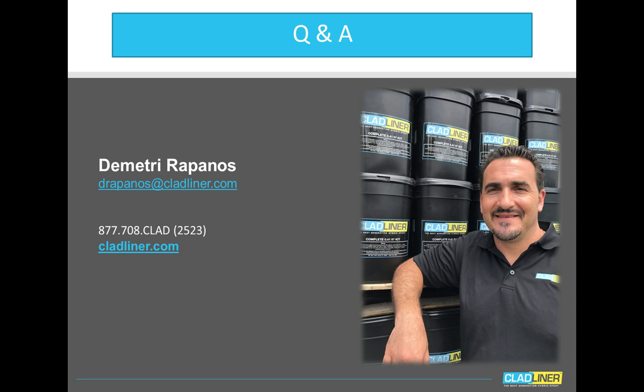Can EMM be used for new manhole construction? Yes, they can. Epoxy modified mortars work really well for new manhole construction. If they're in areas where we are not so concerned with too much I&I initially, because these are all brand new structures, an 1/8 of an inch of the product might be perfect for those kinds of environments. If we're anticipating a lot of I&I in the future, then a 1/4 inch would probably still be recommended. But this is a great product for applying on new structures.